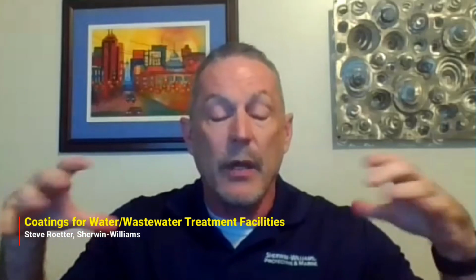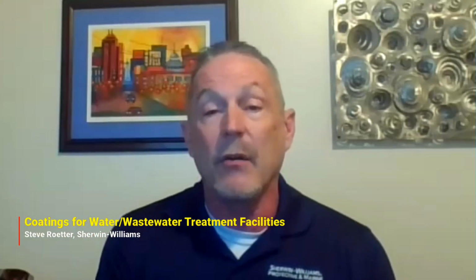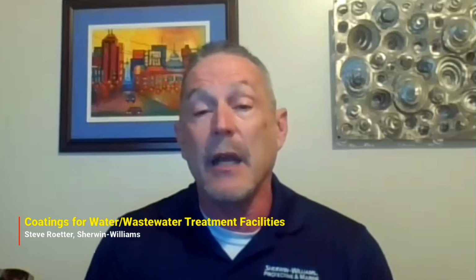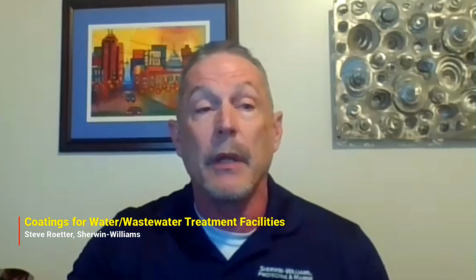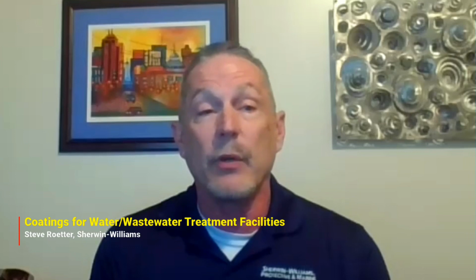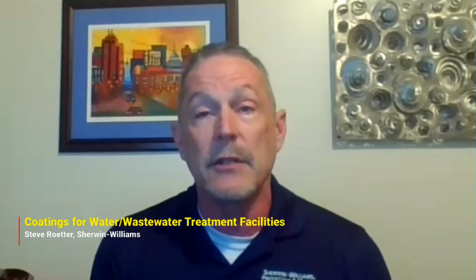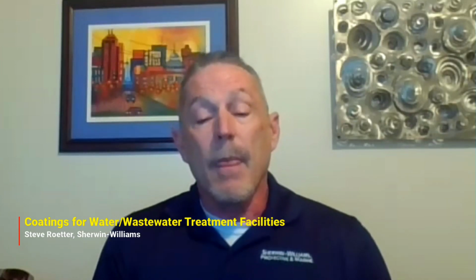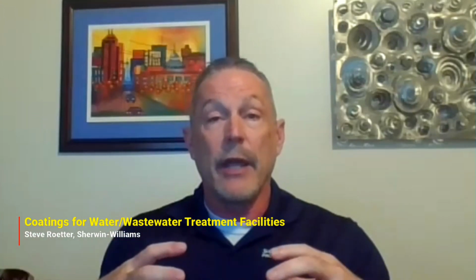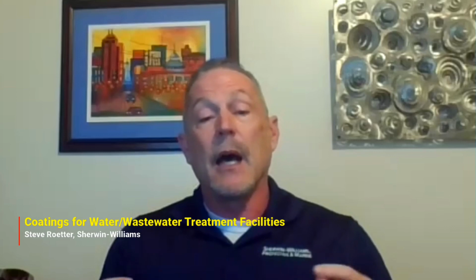Concentrations, you get anywhere from 2 to 10 in the crowns and pump station headspaces, and then in the headworks, you might get 10 or a little above. Now it's not uncommon to see them several hundred parts per million in some facilities, which has made a huge difference. So this has caused a lot of additional deterioration from all this H2S.